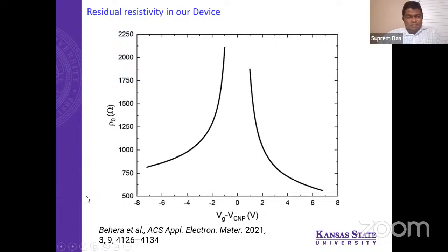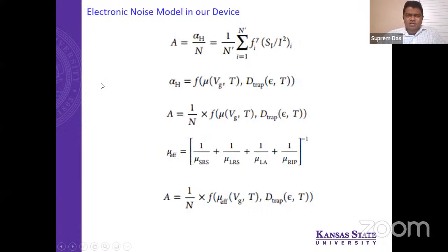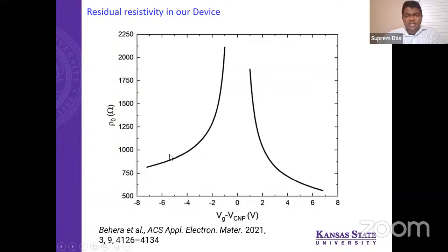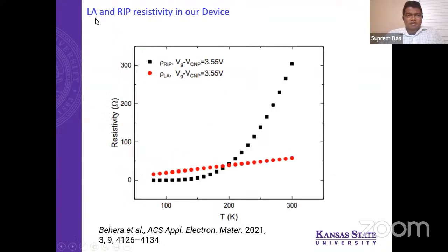Now, independently also, we extracted the so-called residual resistivity. So residual resistivity is basically the resistivity from the short range scattering and long range scattering together. We call it residual scattering. And you can see the residual scattering, at the Dirac point, goes extremely high. And that's where temperature helps us, because if you calculate the longitudinal acoustic phonon contribution to the resistivity and the remote interfacial phonon contribution, then you can see that the remote interfacial phonon also goes very high. So depending on what temperature, you can actually take one of the factors, and eliminate the other factors, things like that.